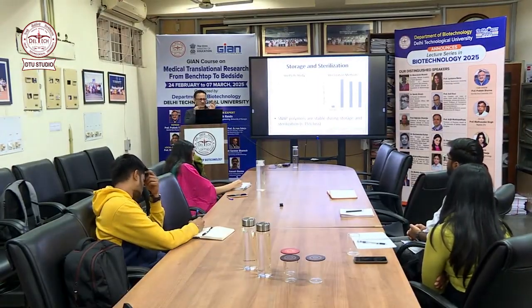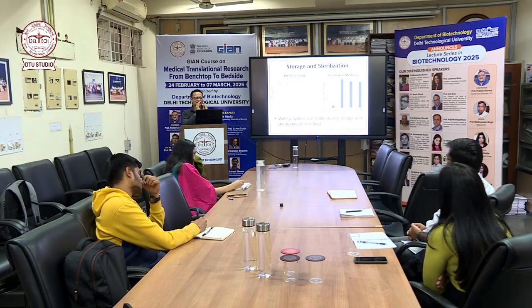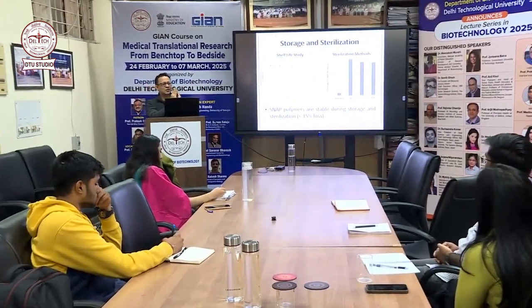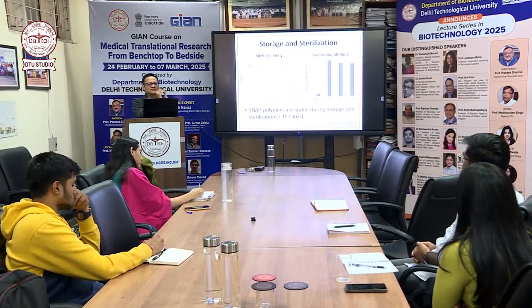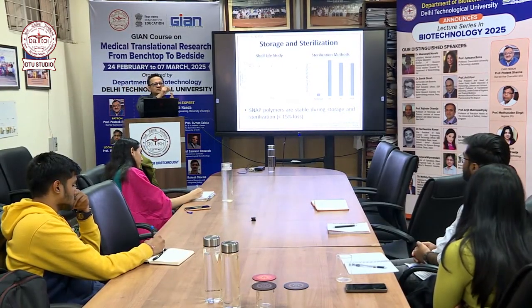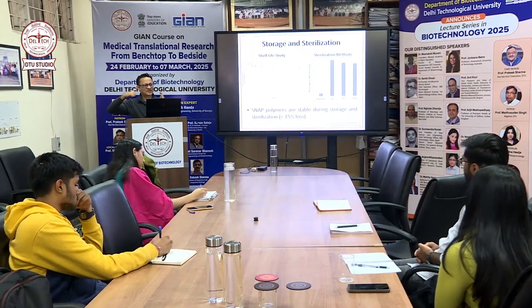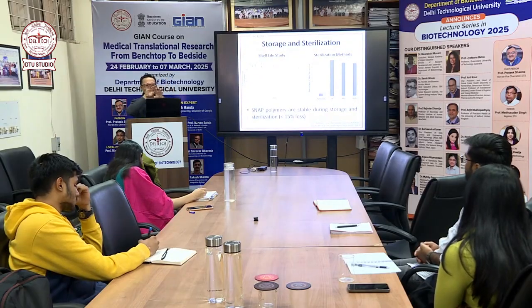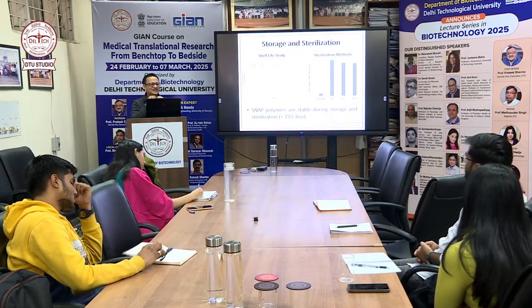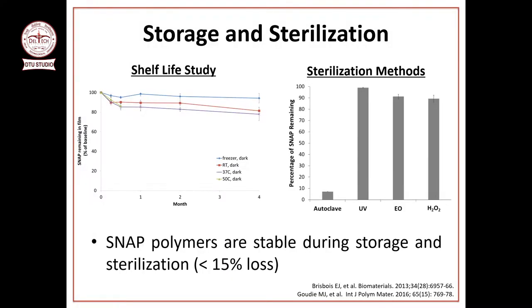But some of the SNAP is not crystallized, a little bit. So what is not crystallized can come out fast. But what's crystallized will release very slowly. When moisture goes inside, it will try to dissolve the crystal a little bit and bring a little bit of NO out. So you saw that little sharp drop because of that uncrystallized SNAP sitting inside the polymer, that came out faster.